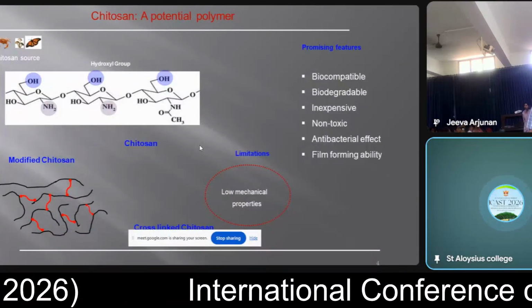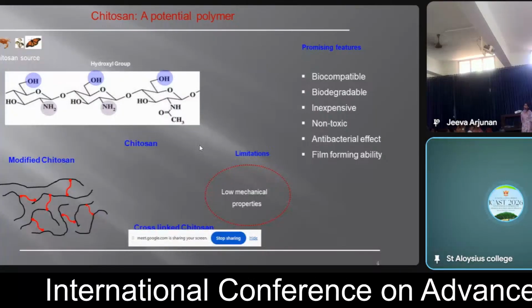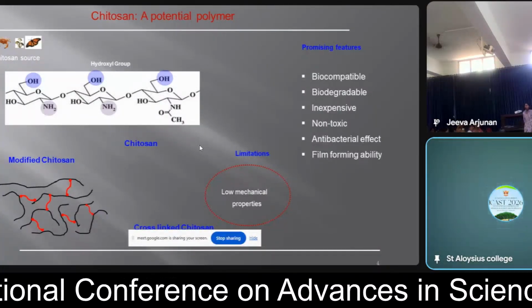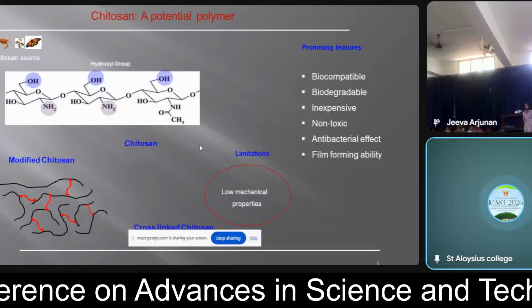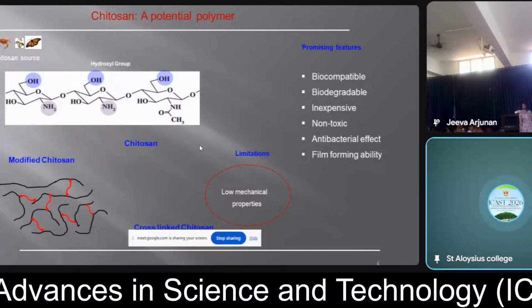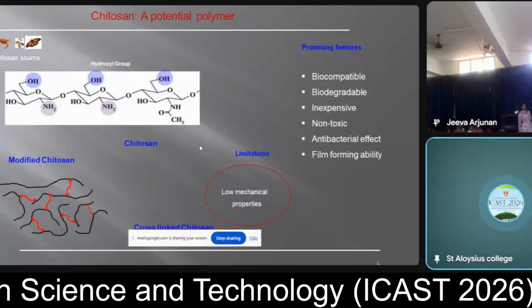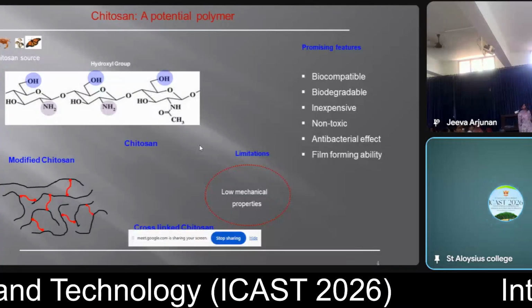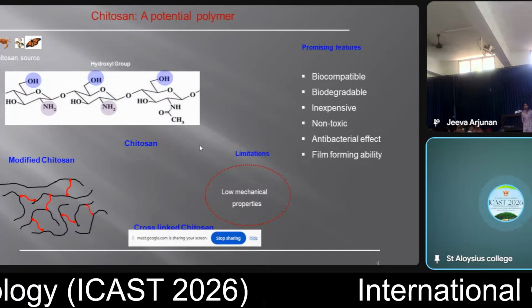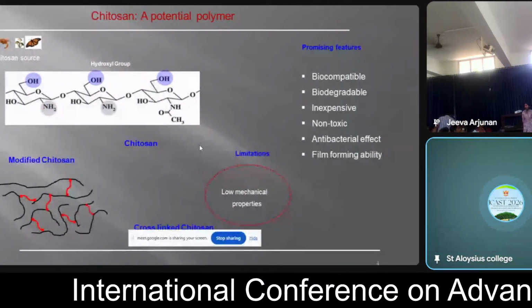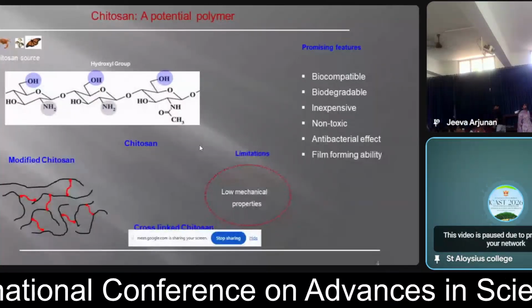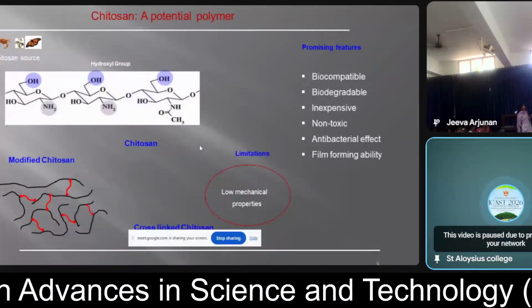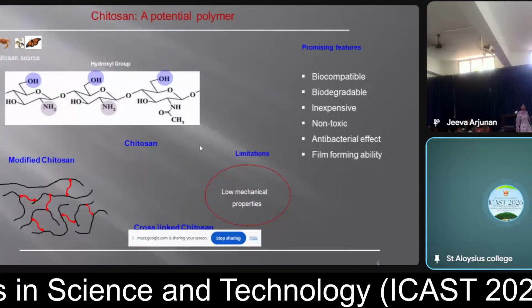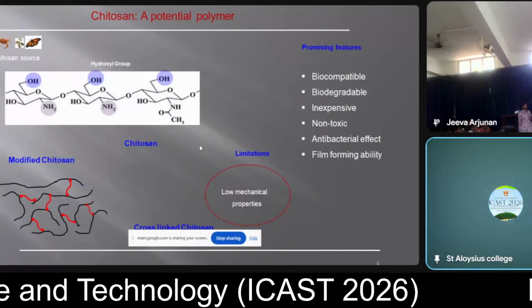The incorporation of polyaniline with chitosan, in response to water. As per the title, the first material is chitosan. Chitosan is a potential polymer. As per its structure, its primary functional groups are amino and hydroxyl groups, which readily form hydrogen bonds. Chitosan itself is not very stable and is brittle and weak, so we can modify it. Here we modified it with glutaraldehyde, so it becomes a cross-linked polymer. Its promising features are biocompatibility, biodegradability, low cost, non-toxicity, antibacterial effect, and film-forming ability. And as I mentioned before, it has low mechanical properties.